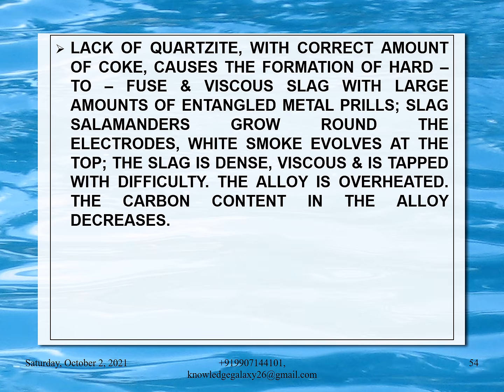Another problem is lack of quartzite with correct amount of coke, which causes the formation of hard to fuse and viscous slag with large amounts of entangled metal prills. Slag salamanders grow round the electrodes. White smoke evolves at the top. The slag is dense, viscous and is tapped with difficulty. The alloy is overheated. The carbon content in the alloy decreases.